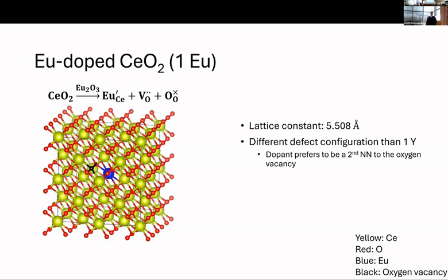We've been working on some other things in parallel where we put rare earth oxides in the uranium oxide, and have seen that the size of the lanthanide makes a tremendous difference in how it oxidizes. And europium being kind of in the middle, I would think that this one would have a strange effect. I mean, with the ceria matrix, you don't have a 5+ cation.